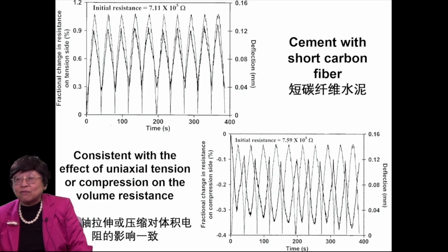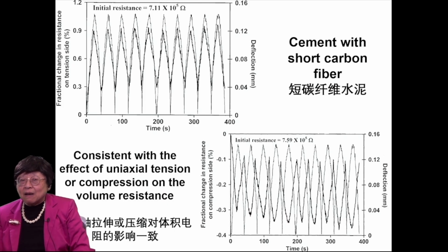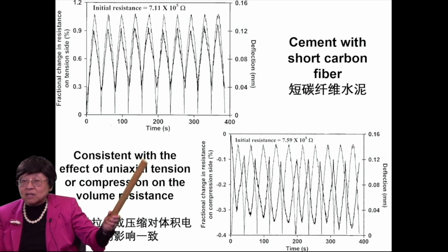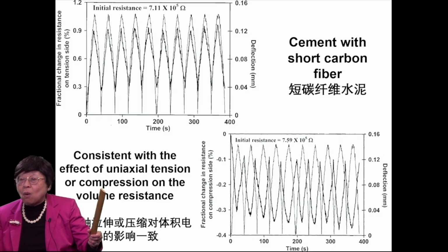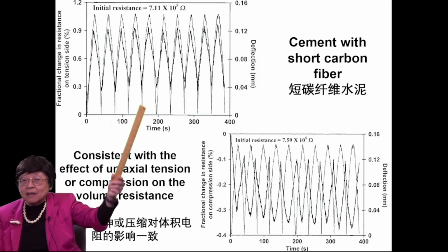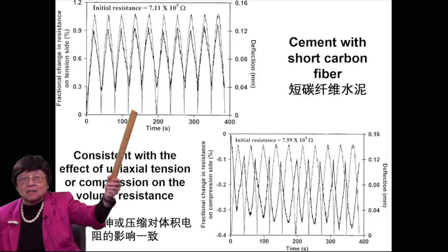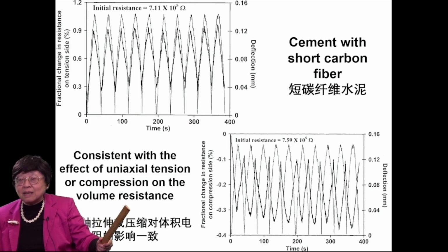So these results for carbon fiber cement are consistent with what I said earlier for the carbon fiber reinforced polymer. And also, it is consistent with the effect of uniaxial tension or uniaxial compression on the volume resistance. That is, under uniaxial tension, the resistance of the short carbon fiber cement increases. Under uniaxial compression, the volume resistance decreases. So the effects on the surface resistance under flexure are consistent with the effects of uniaxial tension or compression on the volume resistance.